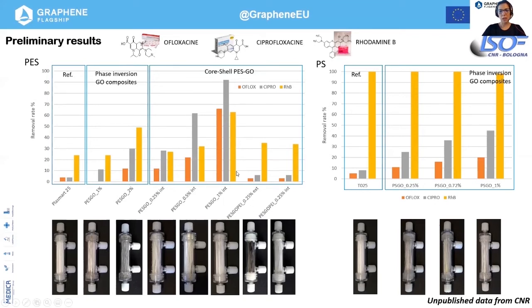Here we are still at a lab scale on small prototypes, but we can see a trend showing a best performance where there is a higher percent of graphene oxide embedded into the fiber. With respect to the core shell GO composite, the phase inversion composite is less efficient, probably due to the loss of graphene oxide during the phase inversion process, meaning that in the near future we need to focus on maximizing the exposure of graphene oxide to the water flow and on the stabilization of this process.